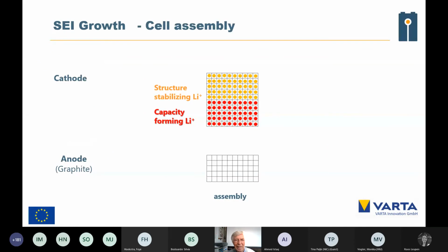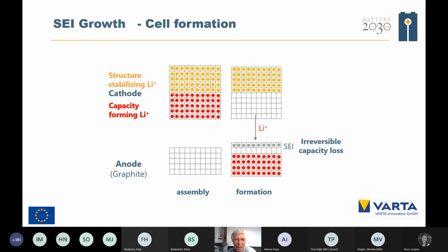So, and now we have the assembly. We have the cathode with the structure stabilizing and capacity forming lithium. And in the assembly, we have the empty graphite. So, and now we are putting the electrolyte in the cell and charging the cell, and then the capacity forming lithium is going into the anode, but not the whole capacity forming lithium, only a part. Another part, the smaller part, is forming the SEI. And that formed SEI, that is the irreversible capacity loss.